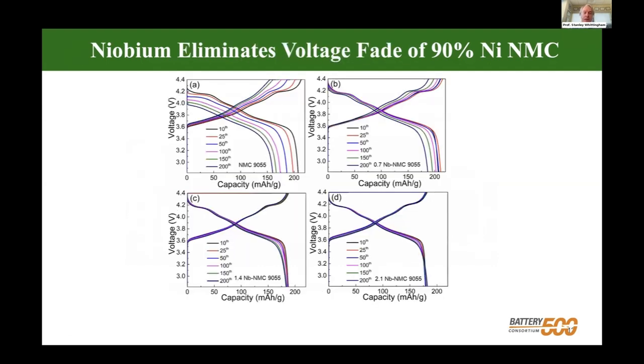We now look at the effect as we cycle these materials. The one at the top here is no niobium. You can see the capacity fade up here. With 0.7 niobium, much less capacity fade. By the time we get to 2.1% niobium, even 1.4, you can see we got no capacity fade at all, no voltage fade. So a little bit of niobium is working wonders with these materials.